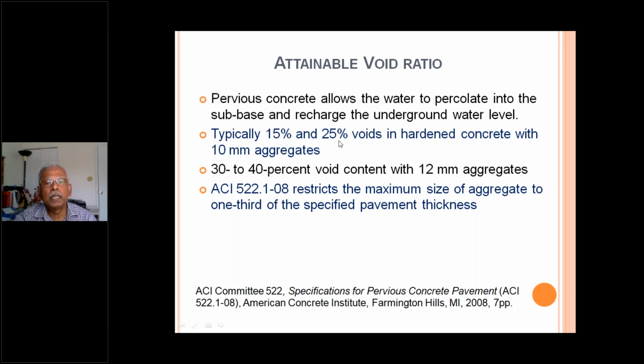As I told you, typical void ratio is 15 to 25% in hardened concrete with 10 mm aggregates, which can increase to 30 to 40% void content with 12 mm aggregates. There is an ACI code, ACI 522.1, which restricts the maximum size of aggregate to 1/3 of the specified pavement thickness. So that is the restriction given in the ACI code.